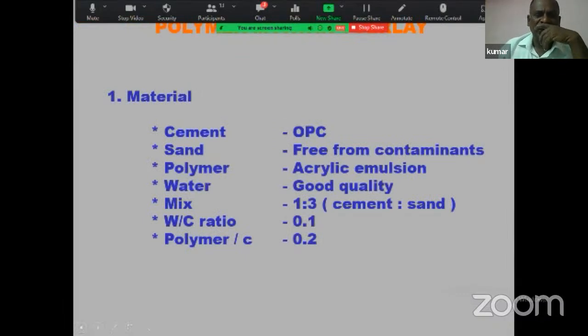So next, polymer overlay. When the shotcrete is over, allow for curing. After the curing is done, within 10 minutes because accelerator is added, then you can go for polymer overlay finish. That is like a cover concrete. People are using the polymer based overlay, that is polymer concrete kind of thing. A polymer can be added into the normal mortar. Generally what we specify: cement OPC, sand free from contaminants, river sand used, and polymer acrylic emulsion used, and good quality water. It is a water soluble acrylic polymer, and mix 1:3 ratio, water cement ratio is 0.1, and polymer cement ratio is 0.2. These are the materials selected for the polymer overlay.